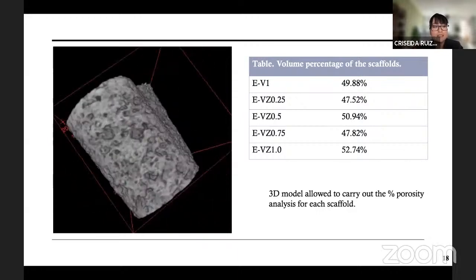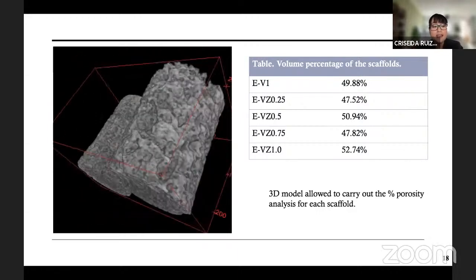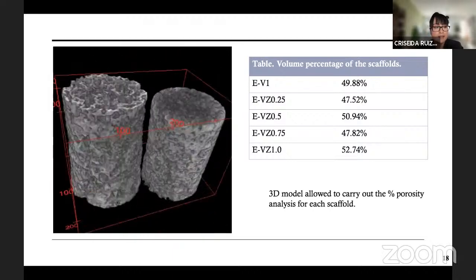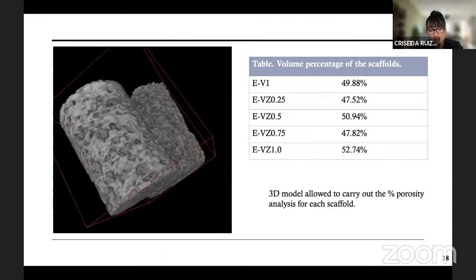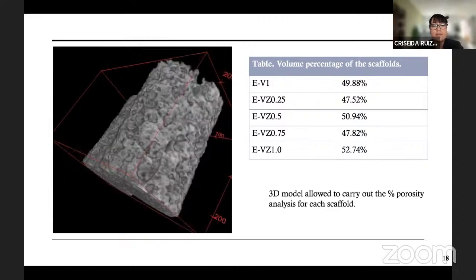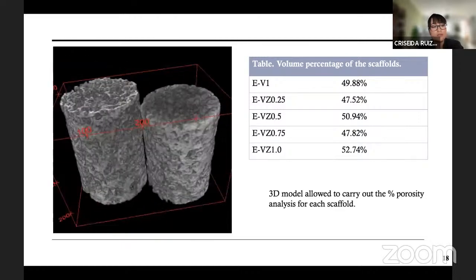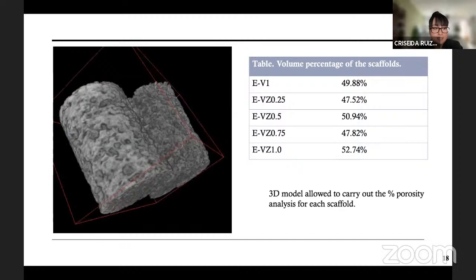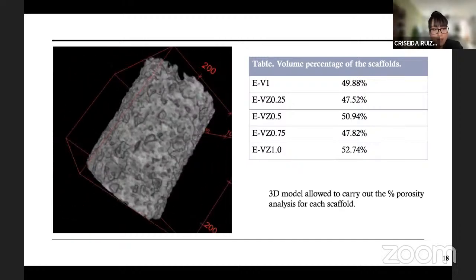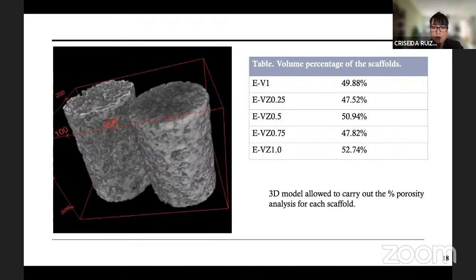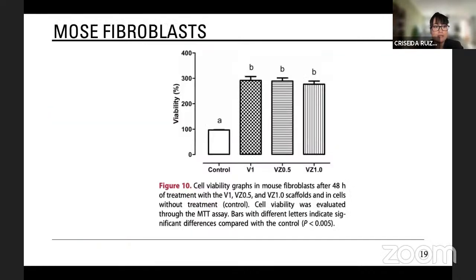For the porosity analysis, 2D cuts of the scaffolds were made using X-ray microtomography, and then a 3D model reconstruction was made, as you can see in this video, which allowed us to obtain the porosity percentage, varying from 49 to 52%. The range of the porosity is a consequence of the wide pore size distribution. In the in vitro part, the scaffolds were evaluated with fibroblasts to analyze cell viability, showing a greater increase in cell viability in the amorphous or porous scaffolds than in the control sample.